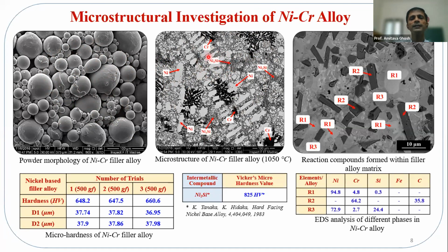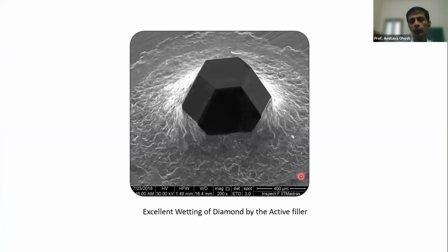These nickel silicides have a tremendous hardness, that's 825 HV. When the bulk hardness is 650 or so, the nickel silicides' contribution alone is 825. Nickel is a much softer matrix. So this presence actually makes the filler material very strong after solidification, much harder as well as quite strong. Okay, so this is how it behaves when it solidifies.